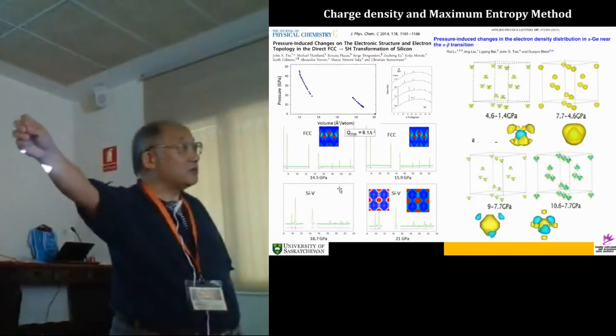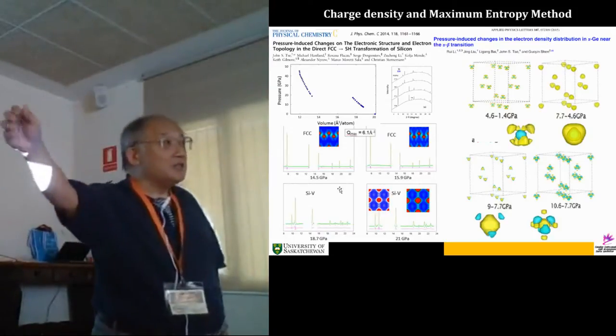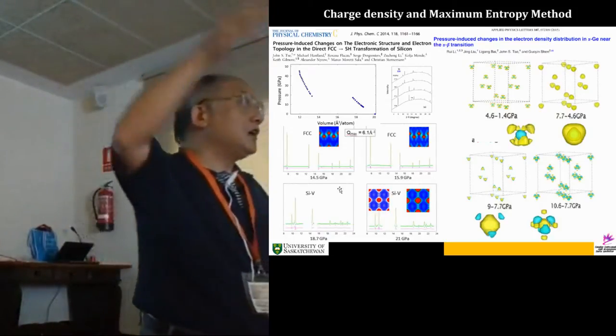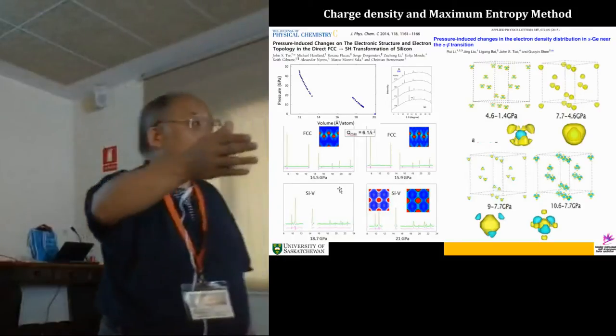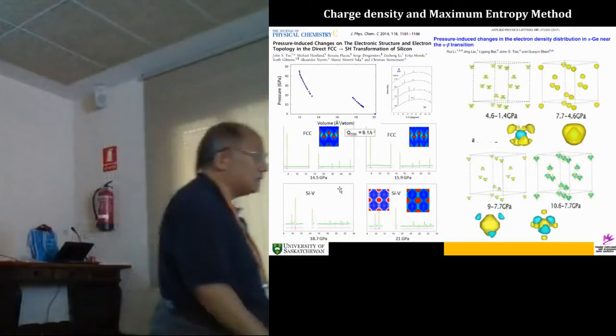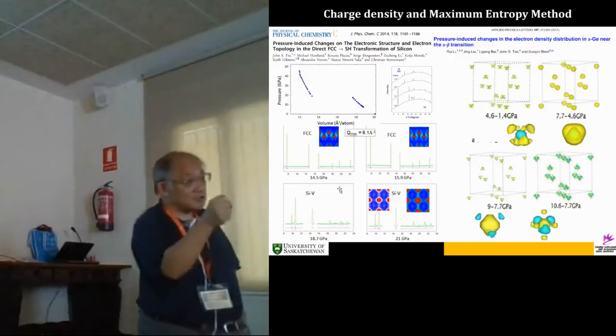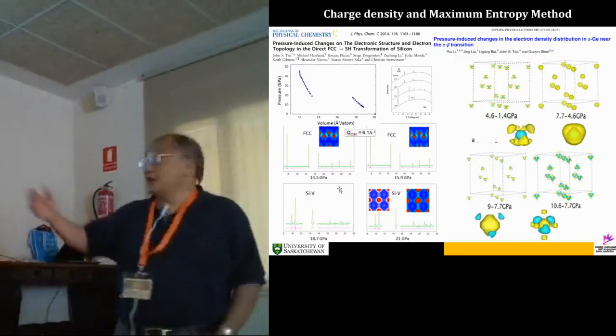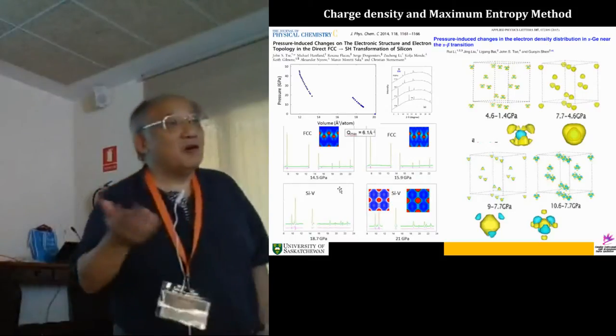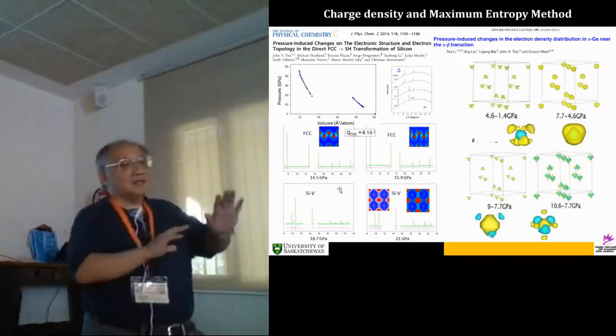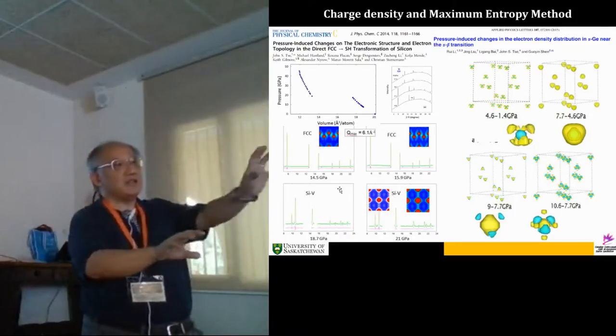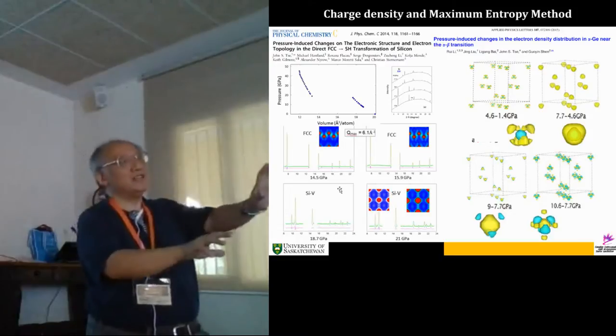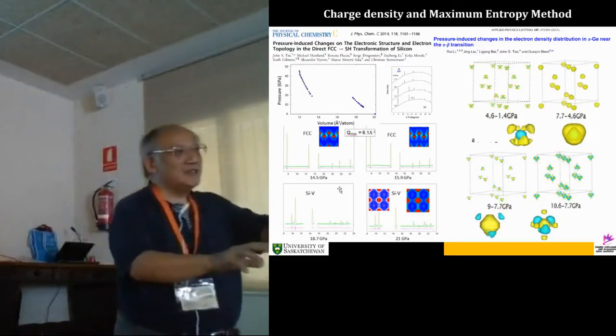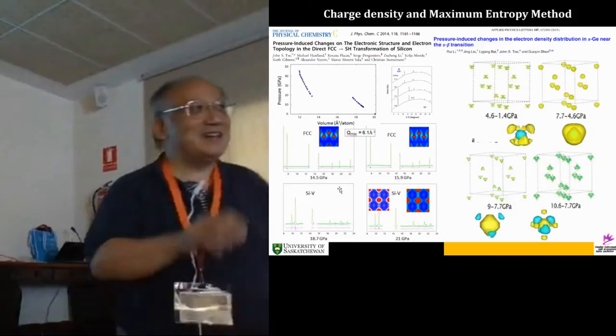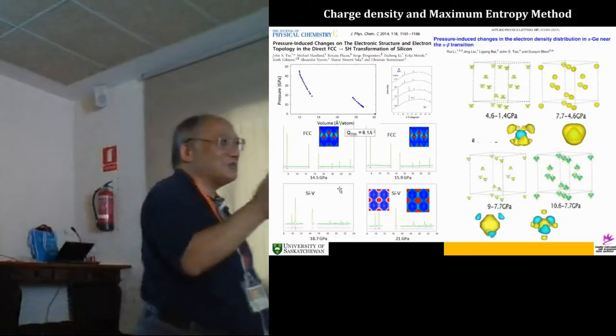So when I was doing my crystallography as an undergraduate, you had to collect very, very high angle data. In fact, if you want to fit a good unit cell size, you never use the low angle data, you use the high angle data to get an accurate one, because it's more concentrated by the core electron. It turns out the maximum entropy method is perfect for this situation, because you can always write the equation of the scattering factor due to the valence electron and the core electron, and they are separate in Q range. That means the 2 theta range. So you take the low angle data, you only look at the valence electron distribution. That's the beauty of it.